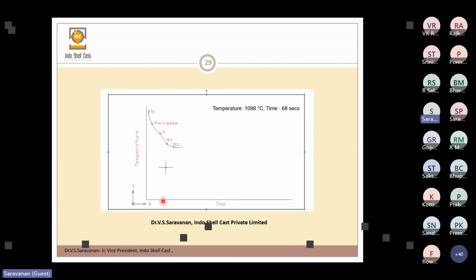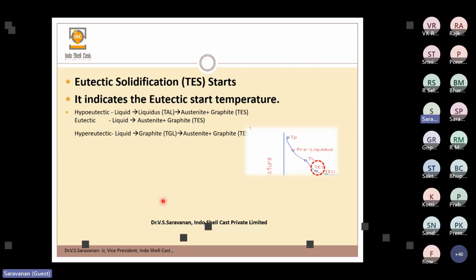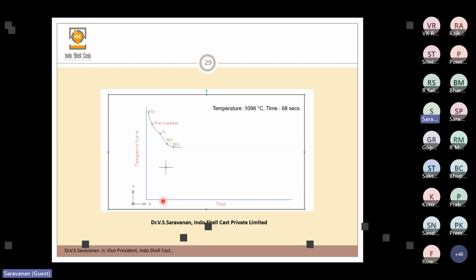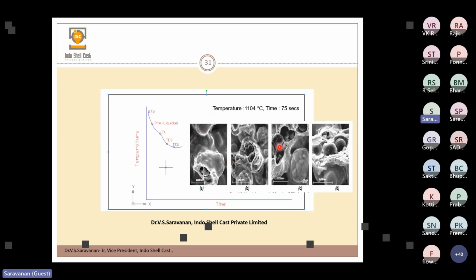And then TEU, so that is the undercooling. Here almost both the things start, the 80%, 70% of graphite and austenite is precipitated here. So TEU. The difference between TL, TES and TEU is very important. What is the temperature difference between TL, TES and TEU? If they are very close together, then the metal is good. If there is a temperature difference and TEU is taking a very long time, then there are chances of getting shrinkage or carbide, all those things. Okay, so you can see the graphites in between the austenite.